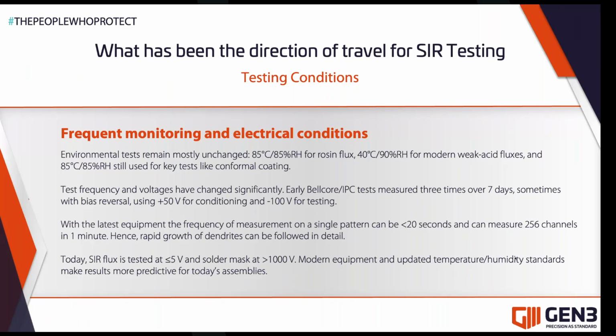Test frequency and voltages have changed significantly. Early Bellcore tests, which go back I think 35 to 40 years ago, measured 3 times over 7 days, sometimes with bias reversal, using plus 50 volts for conditioning and minus 100 volts for testing. But with the latest equipment available today, the frequency of measurement on a single pattern can be less than 20 seconds, and it can measure 256 channels in 1 minute. Hence the rapid growth of dendrites can be followed in detail. Today, some SIR fluxes are tested at less than 5 volts, and some solder masks are tested at more than 1,000 volts. So modern equipment has been updated with temperature and humidity standards, making results more predictive for today's assemblies.